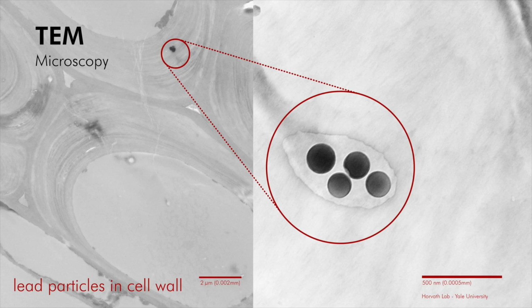And so the way that it captures it, I'm just going to show some TEM, transmission electron microscopy here. So this is really, really zoomed in. You can see those bars down there. We're looking at the particle level there. What you're seeing is the cell wall of the mycelium on the left, and then you basically can't even see the wall because it's so big on the right there, but you can see there are different hyphae, and those little black dots you see there are the lead particles. So these are very, very small particles of lead, and they're lodged within that cell wall.